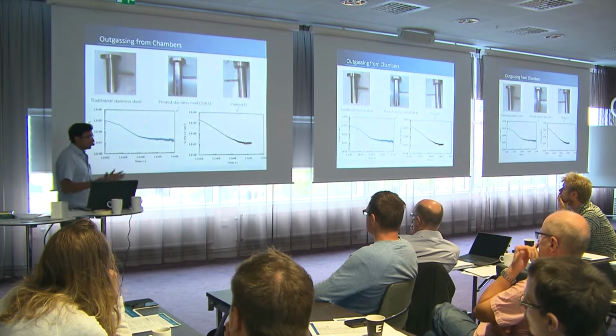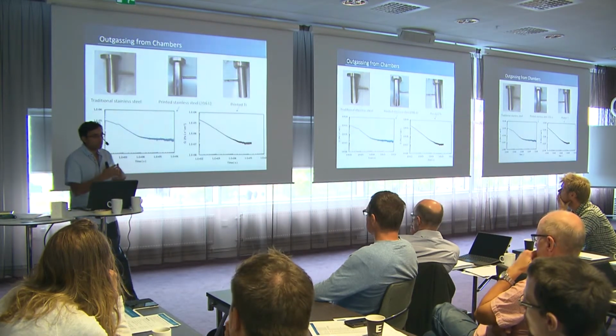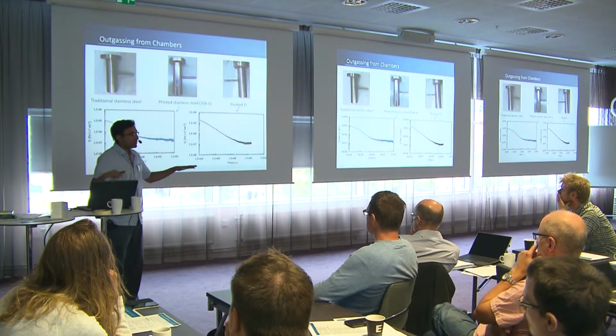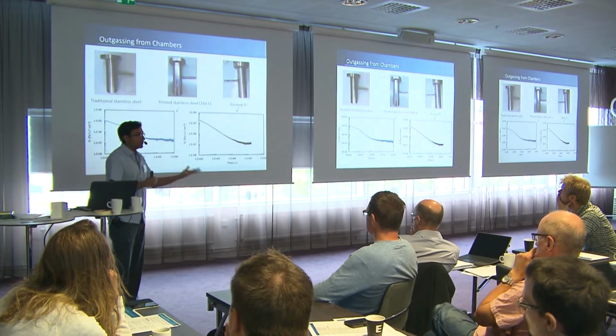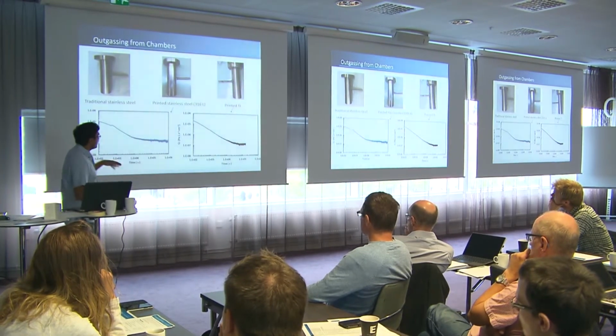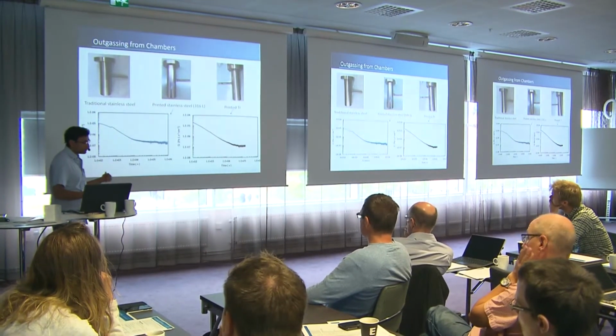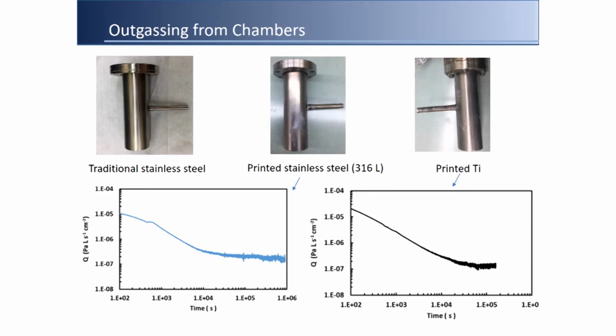What that tells us is that the water molecules coming off of these are just interacting with each other, or just with a bare surface. Their activation energies don't seem to be very different from what you have typically seen in materials. Right now, we have experiments going on looking at the activation energies of water. We're doing the same pumped on curves at different temperatures to be able to extract those. That work is still underway.